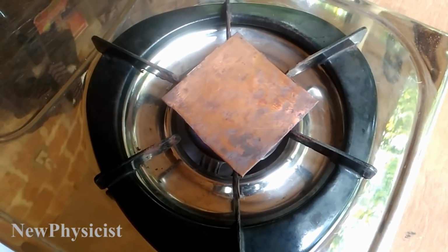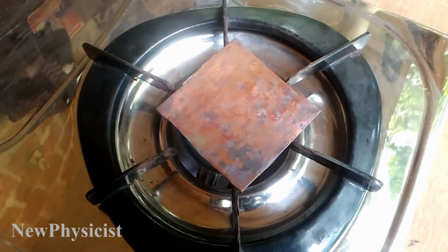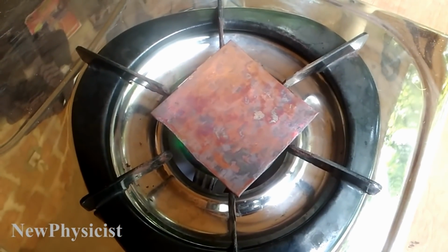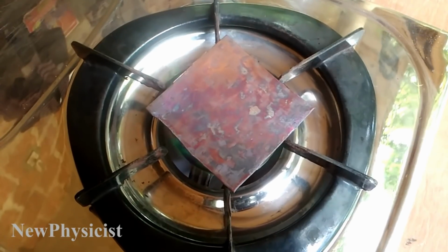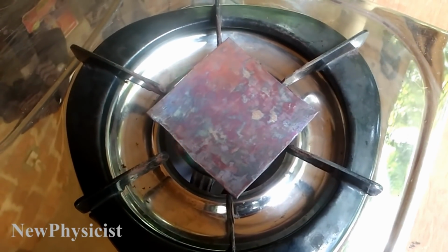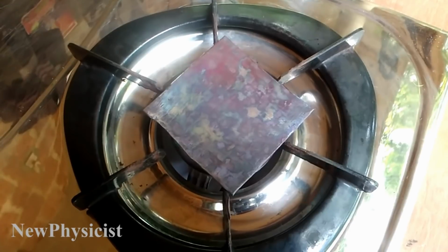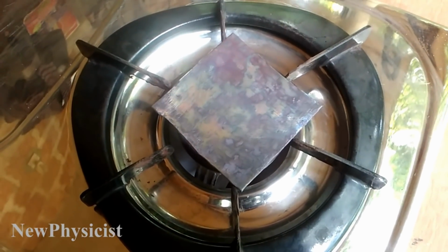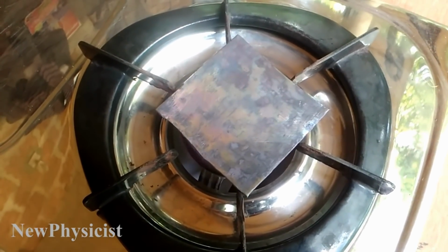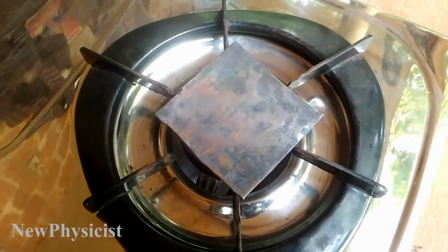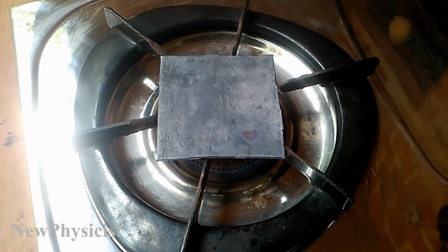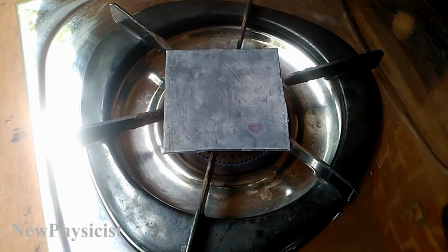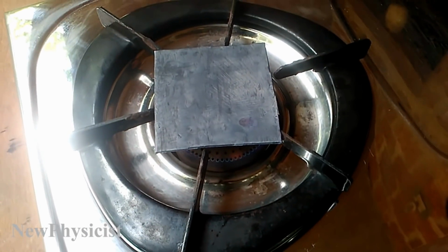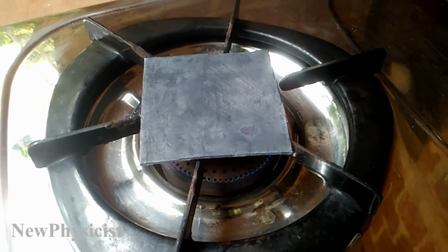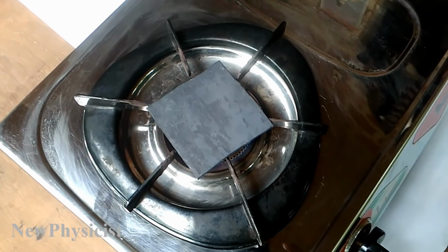As the copper heats up, you can see varying shades of red, pink, purple and possibly other colors. This is a sign that oxidation is taking place. Finally, you will notice that these colors are all being replaced by a black covering. This covering is cupric oxide. Once the whole sheet is covered in cupric oxide, allow it to cook at least 30 more minutes. Cooking the extra 30 minutes makes the cupric oxide layer thick and brittle. This allows it to break away from the copper very easily.